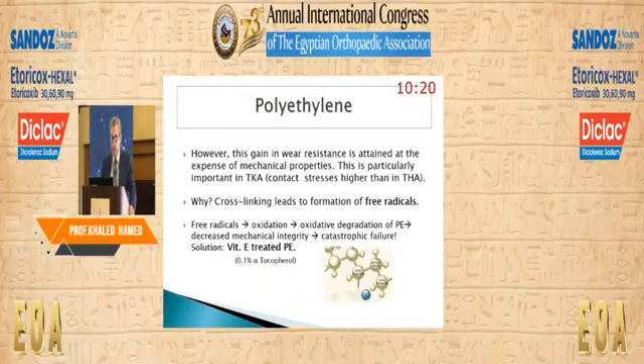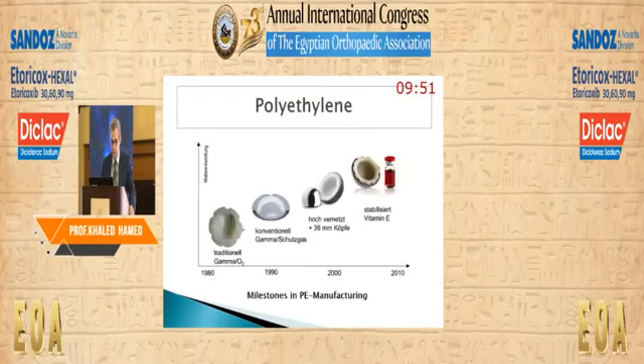However, this cross-linking improves the wear resistance, but at the price of mechanical properties. Why? Because the cross-linking leads to the formation of free oxygen radicals that can cause oxidative degradation of polyethylene. This can lead to catastrophic failure, especially in total knee replacement. And the solution is now using vitamin E treated polyethylene, because tocopherol is an antioxidant, so it grabs these oxygen radicals. These are the milestones in polyethylene manufacturing, from traditional polyethylene up to vitamin E stabilized polyethylene.